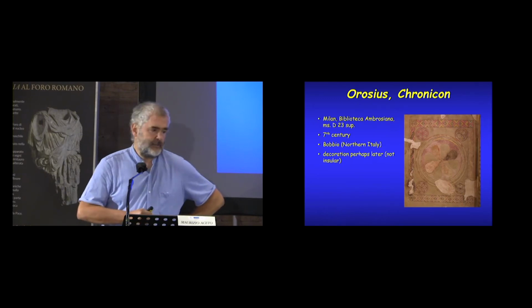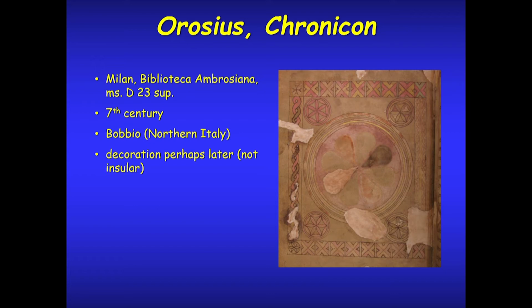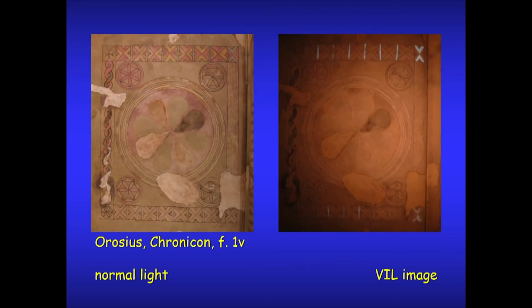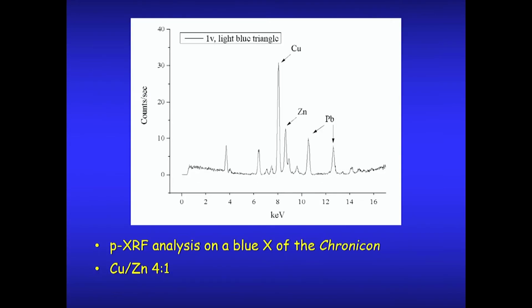And the third case is 7th century, a Chronicon by Orosius, kept at the Biblioteca Ambrosiana in Milan. According to the scholars, it comes from Bobbio, an important abbey in northern Italy, founded by San Colombano, a monk coming from Ireland. This page at folio 1 verso has a decoration which is not insular indeed, so most probably the decoration was added later. But at any rate, the point is that we have again Egyptian blue, a very strange use again. And as you can see, there are some remains still visible under the microscope. The point is that we have again the same result. Copper to zinc 4:1.